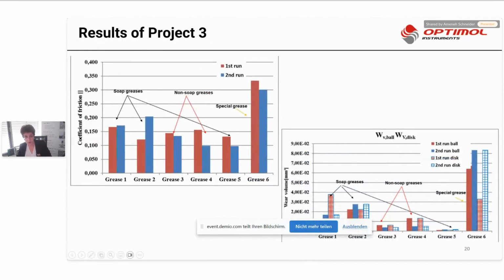I summarize for you all the results of these 6 greases. I made two groups. Let's say we compare now the soap greases and non-soap greases, and this exotic one without any additive, which obviously has the highest friction and highest wear value. For both groups we have done two tests, and in this case, I would say the best one is grease number 5, polyalphaolefin and a special anti-wear additive, also reflected in the very, very low, very nice wear volumes after this test.